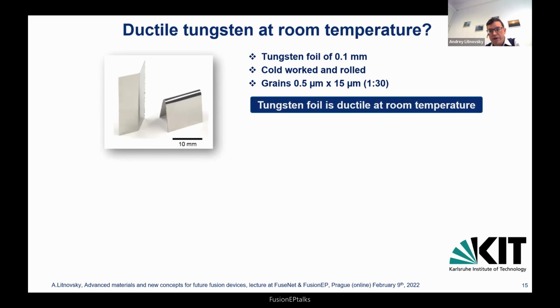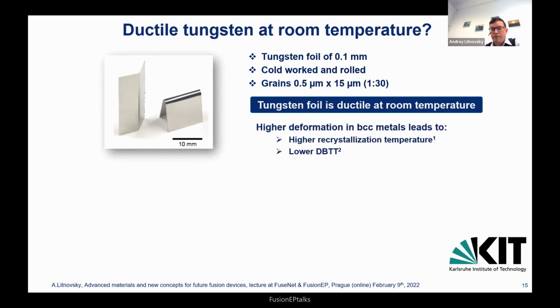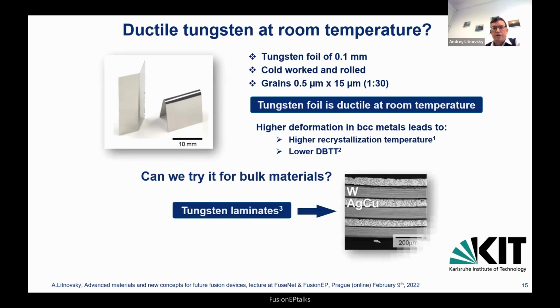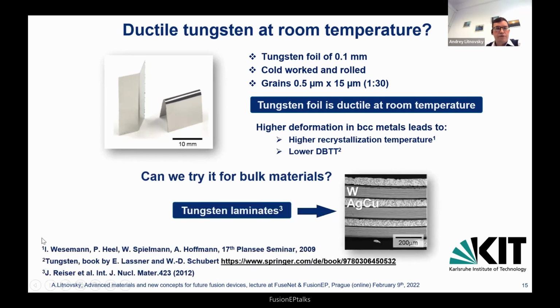So the idea was, why don't we use such a design in order to get components of the bulk material? So this came to the idea of so-called tungsten laminates, which is, as an example, shown here as layered tungsten and in this case the silver-copper eutectic system.